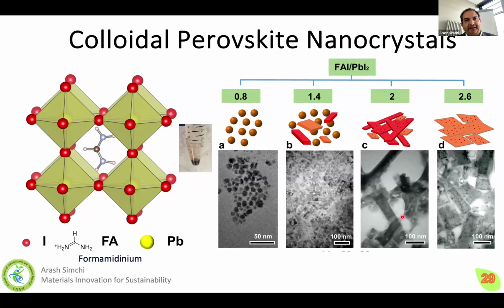But what we have obtained is that we show that it is possible to engineer the shape of nanocrystals just by changing the organic molecules and the cation ratio, as you see here. So we show that by just changing the ratio of FAI to lead iodide, it is possible to change from quantum dots to quantum wells.